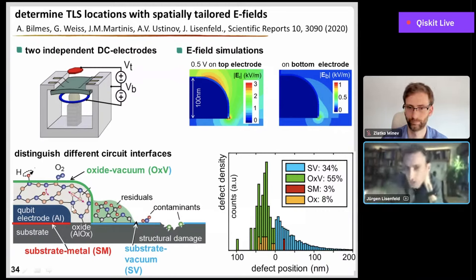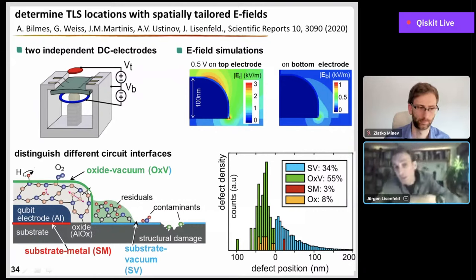So the solution for the position was not compatible with the place inside this oxide layer, simply because they would be coupled much more weakly, a factor of 10 more weakly, let's say. And that's why our solution was that these defects are lying on the very surface of this oxide layer. So these may of course just be amorphous tunneling systems very close to the surface here. So then of course it would still make a difference whether you make this oxide layer epitaxial or amorphous.